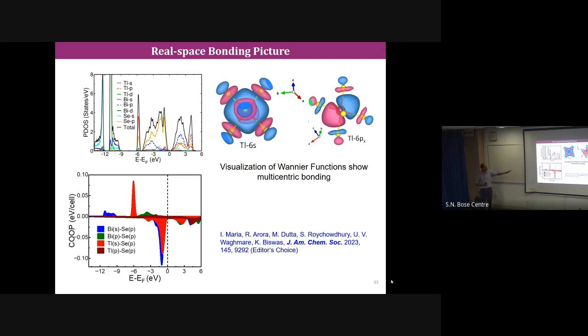So then we have done a calculation called COHP, which tells what the bonding type is. Is it bonding or anti-bonding? For example, in chemistry, if I fill up electrons in an anti-bonding band, the bond becomes much more softened, right? The bond order decreases, right? So to that extent this metavalent bonding comes in this compound, because it is electron deficient for an extended compound.